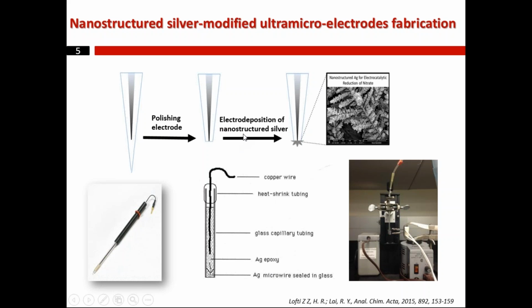Then we started to deposit silver onto the surface of the electrode, and we did this in order to make the electrodes active toward the concentration of nitrate. To do this, we placed the electrodes inside a silver-containing solution, and we applied a negative potential to the electrode, and we forced the silver to deposit onto the surface of our electrode.